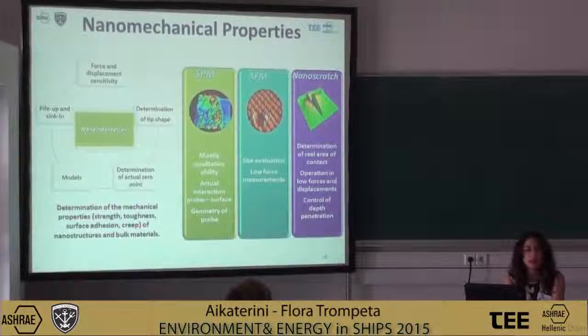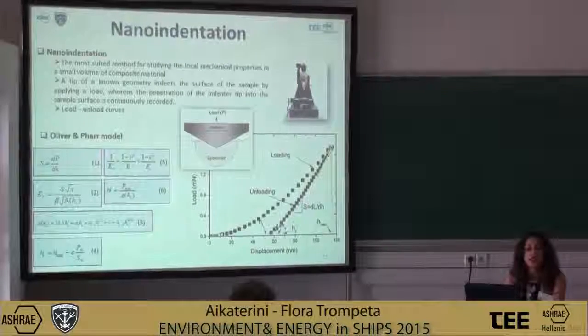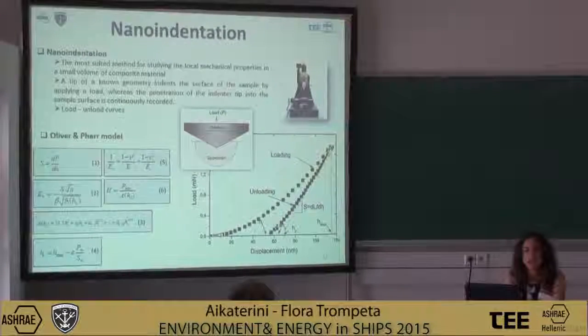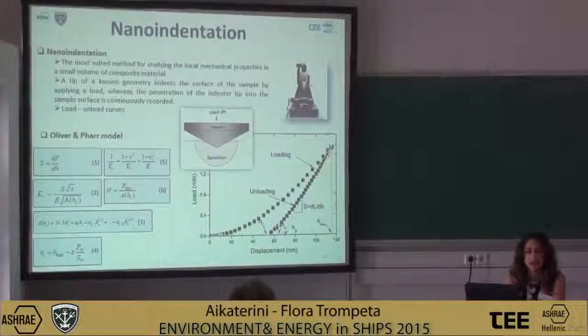A nanoindentation system can determine the mechanical properties of a material, such as strength, toughness, surface adhesion, and creep, as well as we can observe some effects like pile-up and sink-in, or determination of the actual zero point. This technique can also be combined with scanning probe microscopy or atomic force microscopy in order to evaluate the surface morphology. We can also determine the real area of contact with nanoscratch tests.